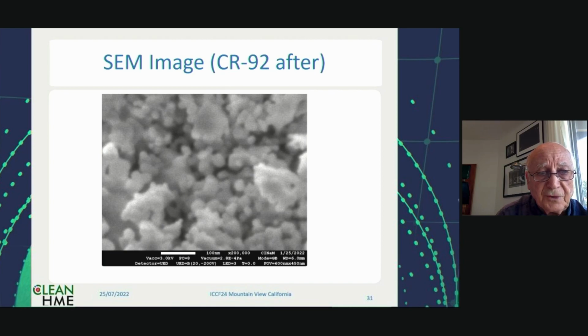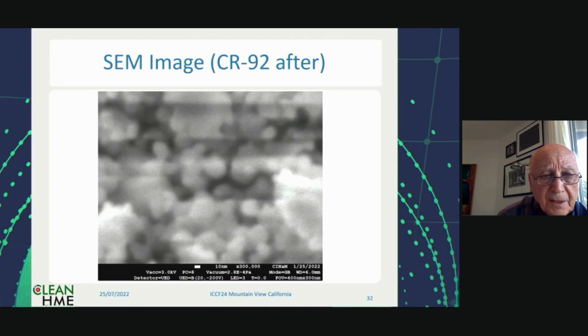Okay, this is a view of the powder after. You see the grain size. With the next slide, we see a better resolution, maybe. Yeah, you see this is about 10 to 20 nanometers size of the nanoparticles. It's slightly bigger than what Arata was showing. He was showing like 5 nanometers. Next slide.